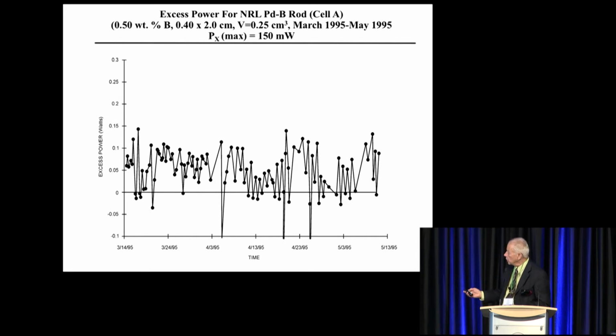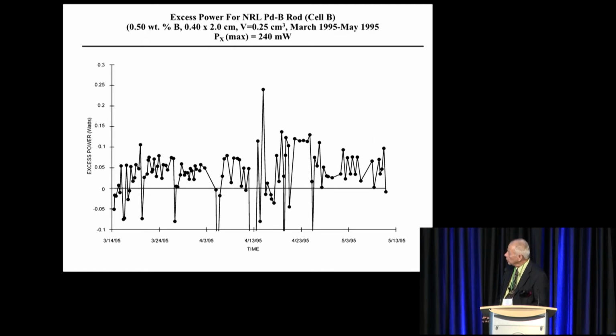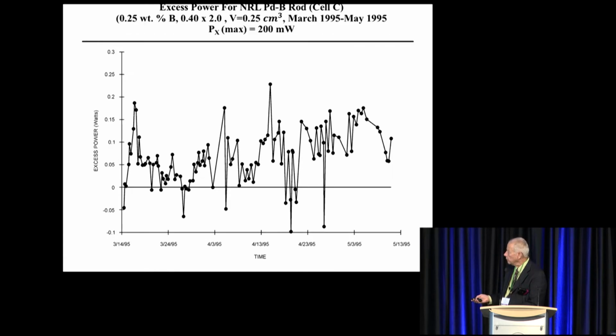These are just more results. Nothing really spectacular there, but it definitely is excess heat above the line. Another experiment, not really great, but still above the line. Again, the point up above there is where I raised the bath temperature. So there's reasons for these little spikes upward, things that I did, like increase the bath temperature, which made the cell temperature above 60 degrees Celsius.